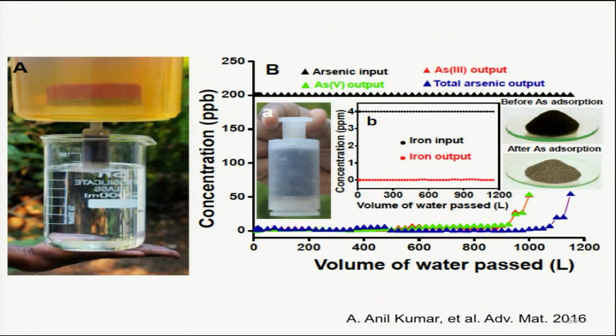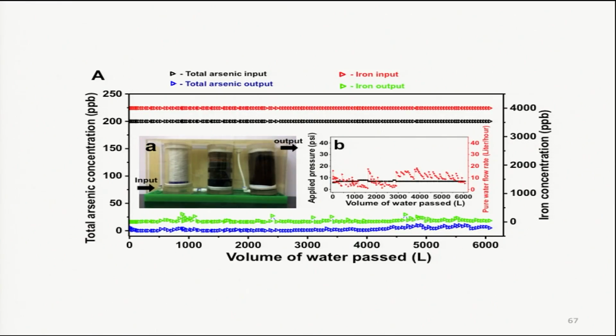So this product, you have about 30 grams of this material, but it removes arsenic from about 1,200 liters of water. And you can make a domestic purifier. And that domestic purifier runs for 6,000 liters.